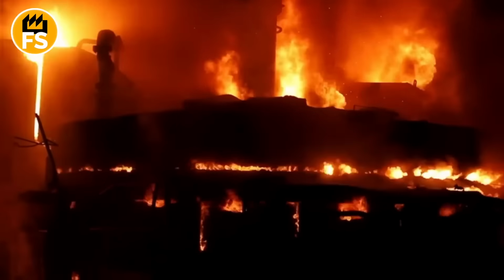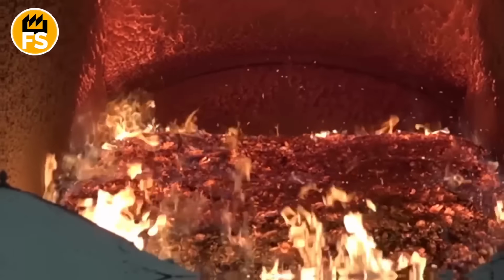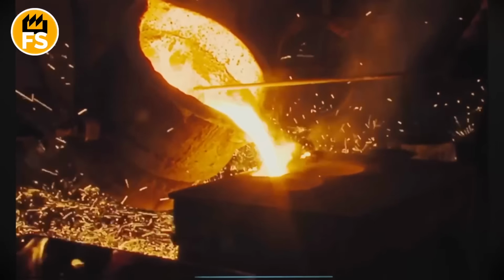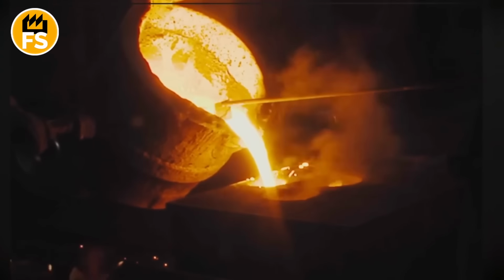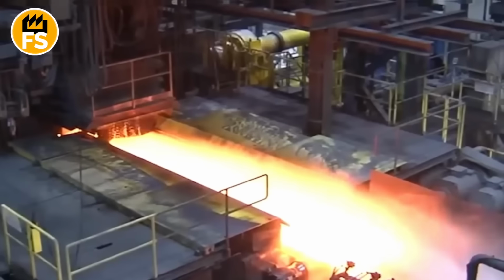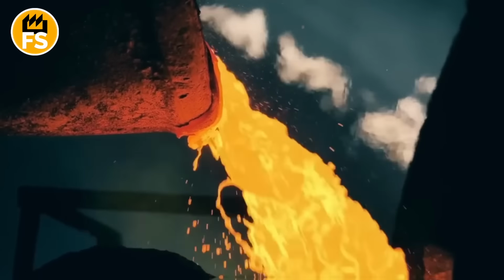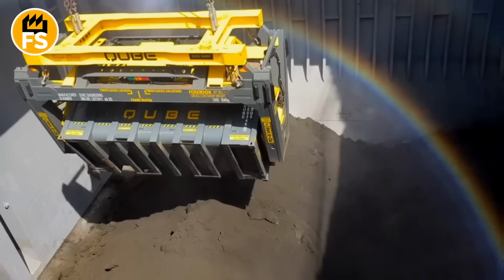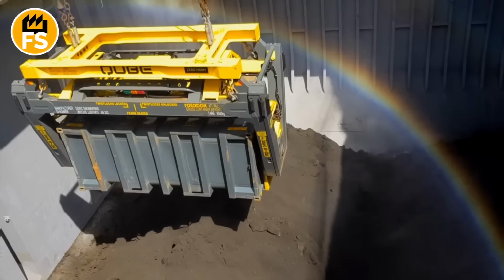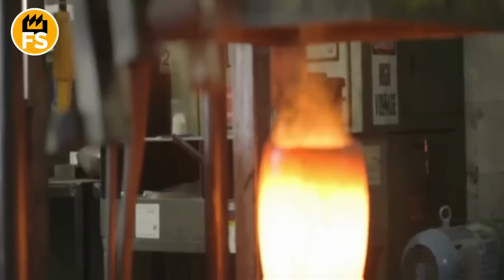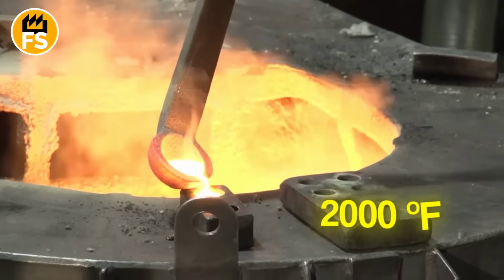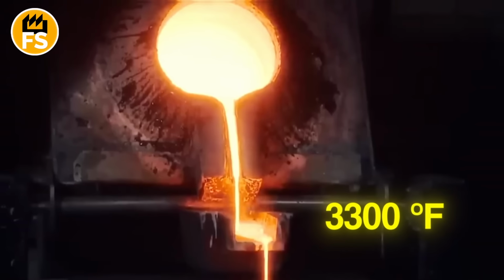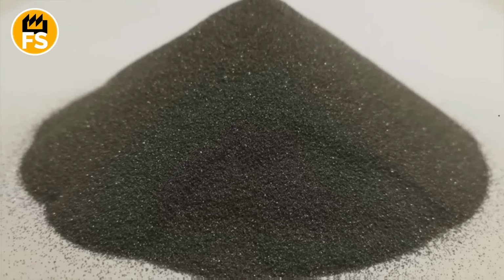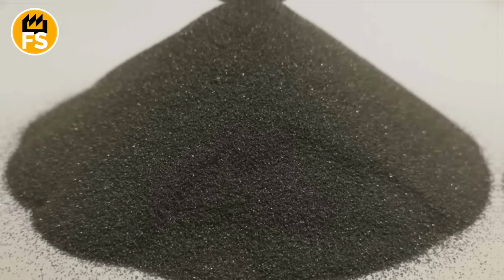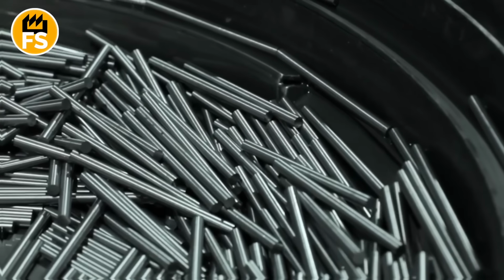The concentrate is then processed at metallurgical plants to extract pure tungsten. It's a complex chemical process that can involve alkaline leaching, precipitation of ammonium paratungstate, and its subsequent roasting to produce tungsten oxide. The tungsten oxide is then reduced to metallic tungsten by heating it in a hydrogen atmosphere at temperatures ranging from 2,000 to 3,300 degrees Fahrenheit. The result is a fine tungsten powder, which forms the foundation for all subsequent products.